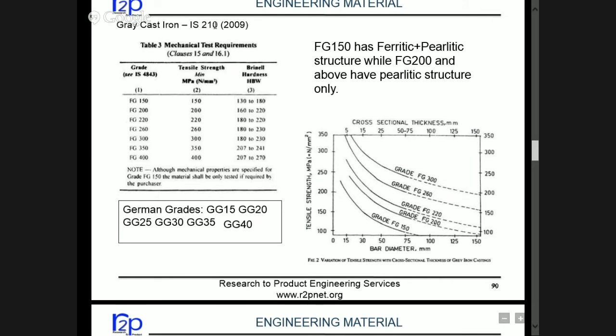Now, as per IS 210, which defines grey cast iron in India, these are the grades I mentioned, some of them. FG150 is almost ungraded, no chemical composition you can assure. So FG150, 200, 220, 260, as I told you, is the most popular. Then 300, 350, 400, which of course are hardly used. Up to 260 it's mostly used. The equivalent German grades are GG15, GG20, GG25. GG25 is equal to our FG260. FG150 has ferritic and pearlitic structure, while FG200 and above have pearlitic structure. So it is desirable to have a pearlitic structure.